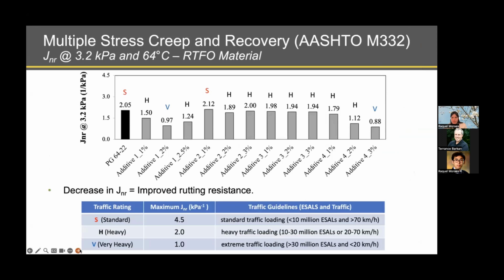And here we have the summary of the results for the MSCR test for the base binder and the graphene-modified binder. Here we have the JNR, creep compliance, where you can see for the base binder, we saw a JNR of 2.05. And for some of the additives, the majority of them, the results were lower JNR in comparison to the base binder, which indicates that the binder is slightly stiffer or harder than the base binder, with exception of the additive 2 at 1% that shows a slightly higher JNR than the base binder, indicating that the binder is slightly softer.